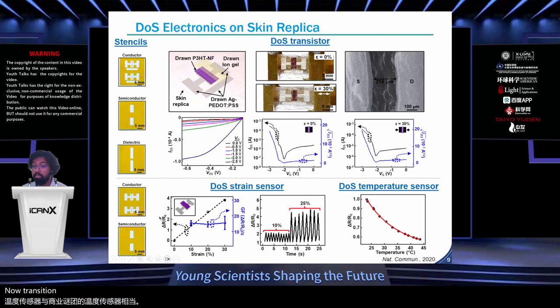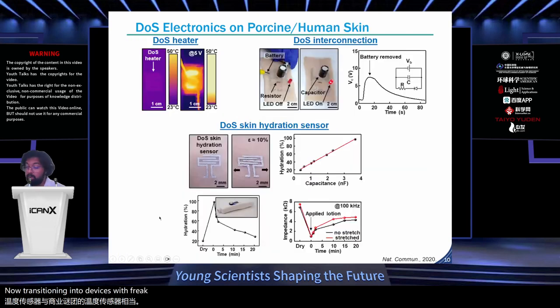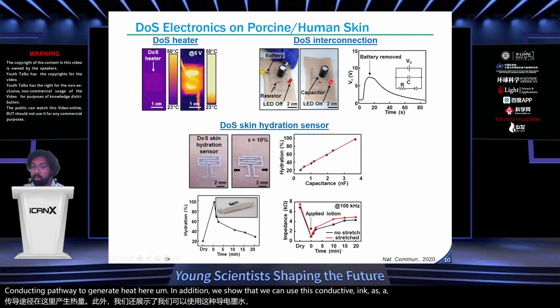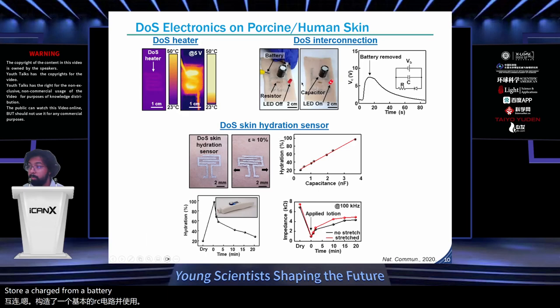Now transitioning into devices which we drew on actual skin, on porcine skin. Starting at the top here, the DOS heater works quite well. The conductive ink serves as a clear conducting pathway to heat here. In addition, we show that we can use this conductive ink as an interconnection. We constructed a basic RC circuit, and we store a charge from a battery. Eventually, after removing the power supply battery, we can discharge.